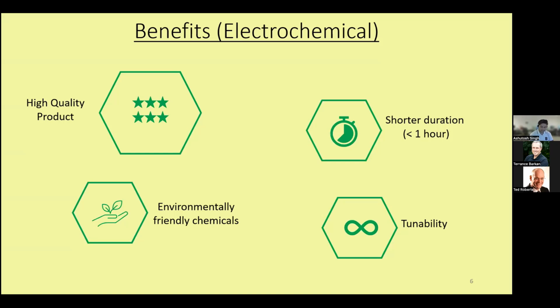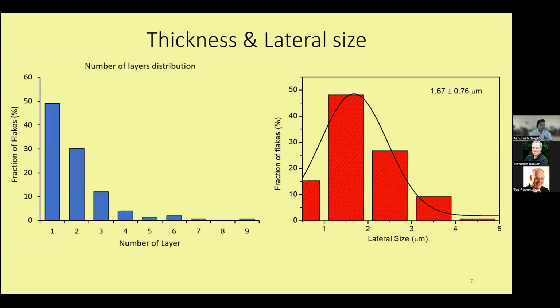Here is some information that our team collected on the thickness and lateral size, which is really important. For example, in one of the chemistries that we discovered and invented in our team, around 80% of the flakes were 1 to 2 layers, with a lateral dimension of 1.67 micrometer. So we were able to produce really high quality material using that chemistry.